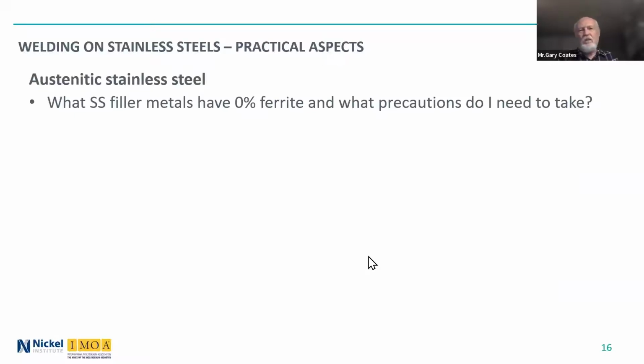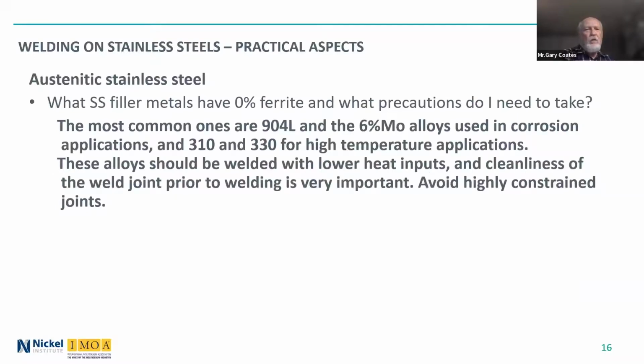So there are some filler metals that have 0% ferrite. So which ones and what do I have to do about those? Well, the most common ones that have 0% ferrite are the filler metals for 904L and the 6% molybdenum alloys, which are used in corrosion applications, and the high temperature alloys such as 310 and 330.